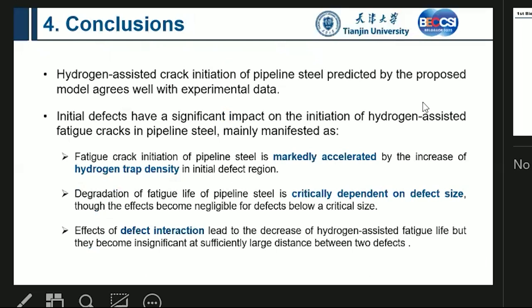So we come to the conclusion here. The hydrogen-assisted fatigue crack initiation of pipeline steel predicted by the proposed model agrees well with the experimental data. And also initial defects have a significant impact on the initiation of hydrogen-assisted fatigue cracks in pipeline steel. Fatigue crack initiation of pipeline will be markedly accelerated by the increase of the hydrogen trap density in the initial defect region.